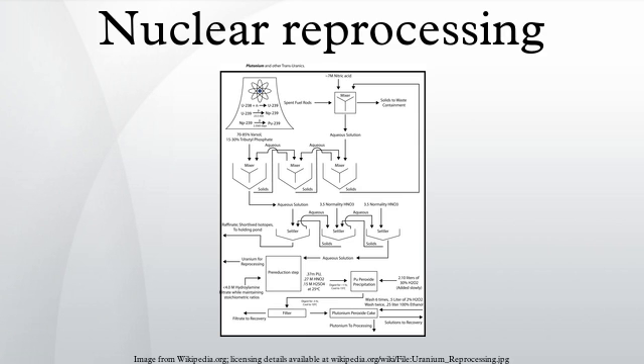UNEX: the universal extraction process was developed in Russia and the Czech Republic. It is designed to completely remove the most troublesome radioisotopes from the raffinate remaining after the extraction of uranium and plutonium from used nuclear fuel. The chemistry is based upon the interaction of cesium and strontium with polyethylene glycol, and a cobalt carborane anion. The actinides are extracted by CMPO, and the diluent is a polar aromatic such as nitrobenzene. Other diluents such as meta-nitrobenzotrifluoride and phenyl trifluoromethylsulfone have been suggested as well.